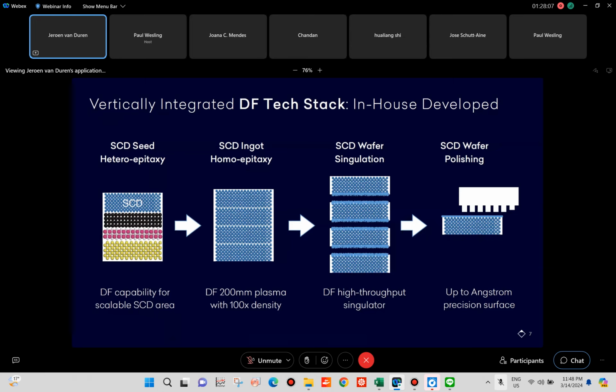Now, how is diamond manufactured? There are 4 very important steps that we have developed in-house, 4 pillars. It starts with seeds. To be able to grow large diamonds, you have to have large seeds. And that's done by heteroepitaxy. So we have a capability to scale the diamond area as a result. Once you have these seeds, you grow ingots, diamond ingots. That's done by homoepitaxy. In our proprietary reactors, we grow over an area of 200 millimeter, which is very unique, with a plasma density 100 times higher than what's commercially available.